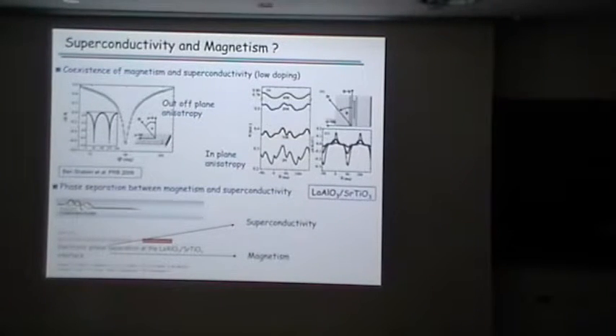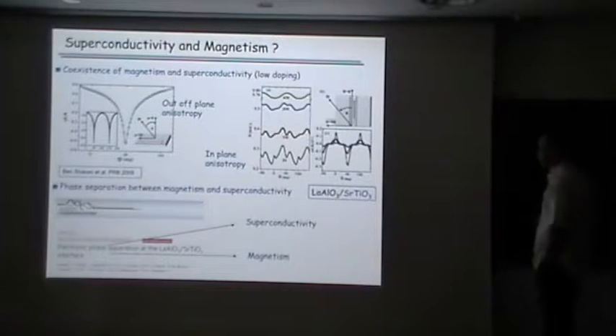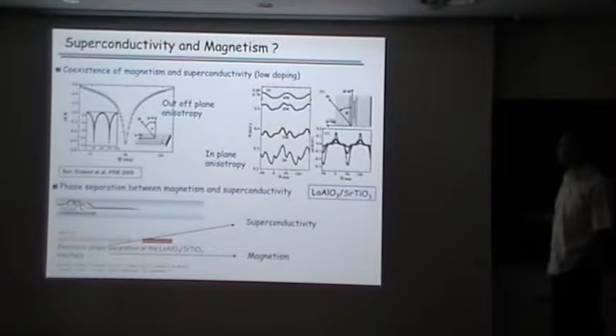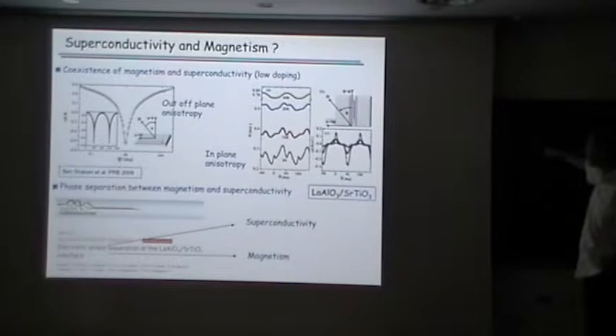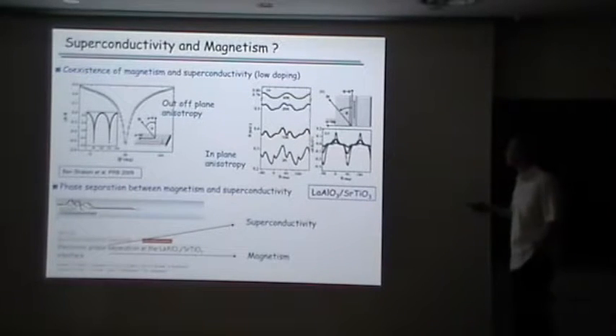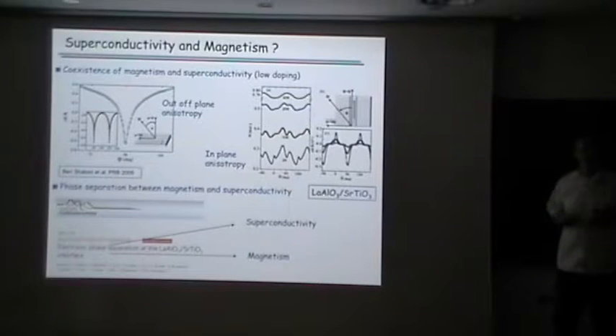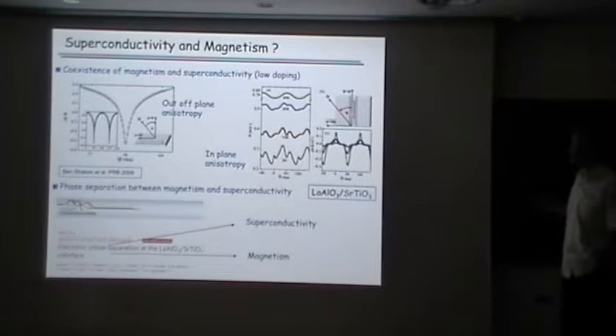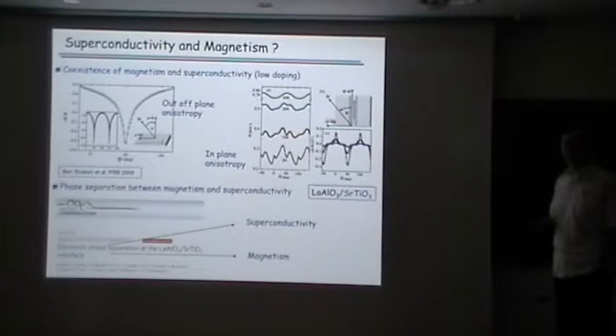For instance, those papers from Dagan's group in Israel, they measure the magnetoresistance of the lanthanum aluminate and strontium titanate system, and they see out of plane magnetoresistance. This is just due to the thickness of the film, but they also found in plane anisotropy. There is an anisotropy depending on if the magnetic field is parallel or perpendicular to the current. And they said that it could be a kind of smoking gun of magnetism, within a type of spin-dependent scattering or something. Again, this is not completely understood, and this is also for very low doping materials.